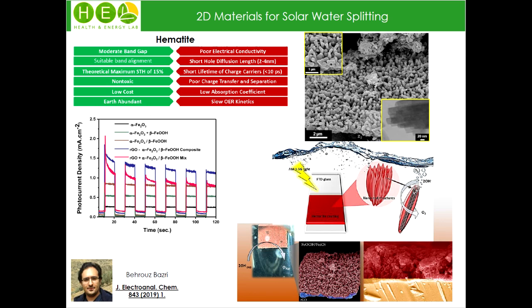He found a one-pot system for producing such ternary composites, and we found that because of oxygen-containing surface functional groups on the RGO, this host could facilitate formation of iron oxyhydroxide nanobelts as a co-catalyst on the surface of the main active material, which was hematite nanorods.